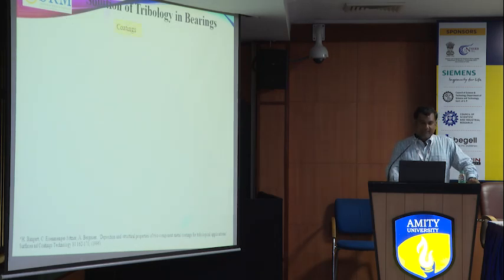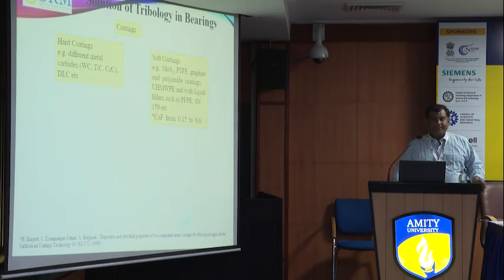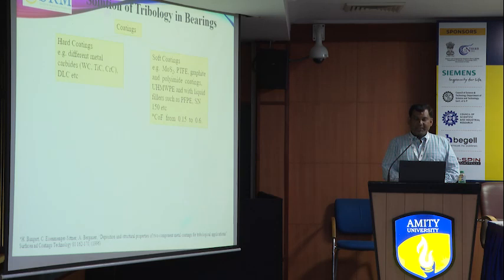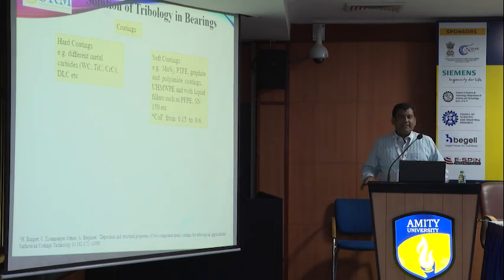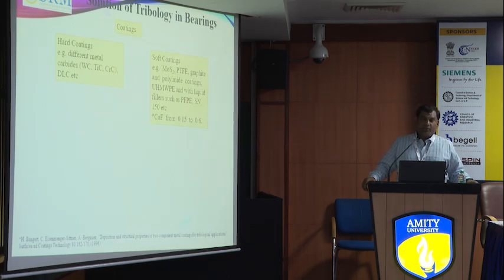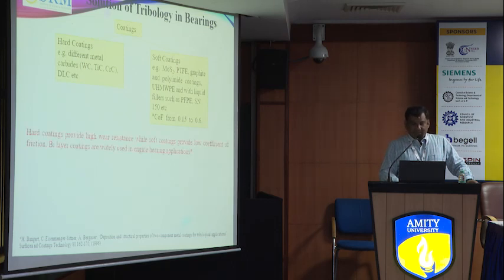Some researchers say coating is one solution. In coating also, there are two types: hard coating and soft coating. Soft coating is good for coefficient of friction, but not good for wear; it will fail fast. Hard coating is good for wear resistance, but not good for frictional coefficient. So what people have suggested in the literature is that we can make a sandwich and use both properties. We can make hard coating, then soft coating, then hard coating and soft coating as per our requirement, a few nanometers each. That was the beauty. Then we can get a low coefficient of friction as well as high wear resistance. So that was the solution proposed by researchers.